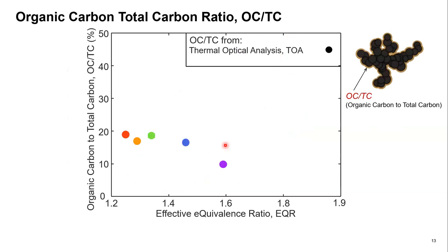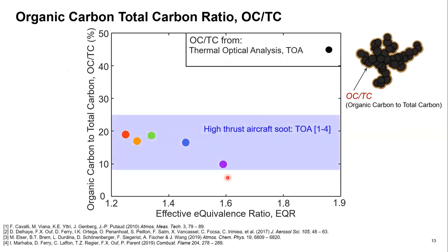The next thing we looked at was the organic carbon to total carbon ratio, first using thermal optical analysis, which is the most common technique used in the field. On the x-axis, we have again the effective equivalence ratio, and on the y-axis, the OC/TC ratio as a percent. So here we see that at the leanest flames, we have an OC/TC ratio just below 20%, and this drops down to about 10% at an equivalence ratio of 1.59. And we see that this is right in the range of OC/TC ratios that we typically expect for aircrafts at high thrust.